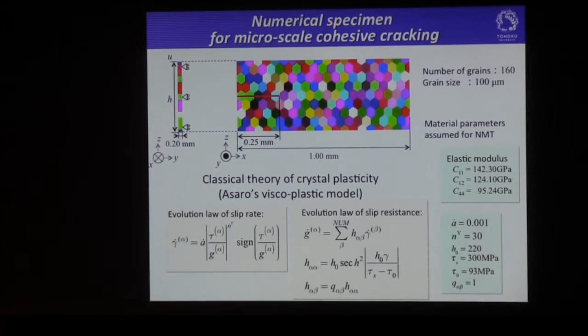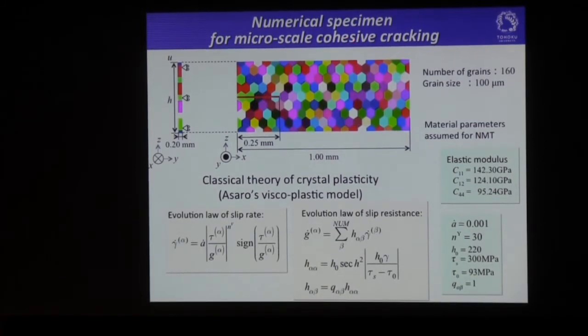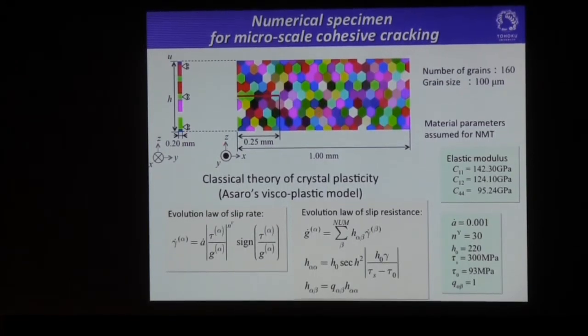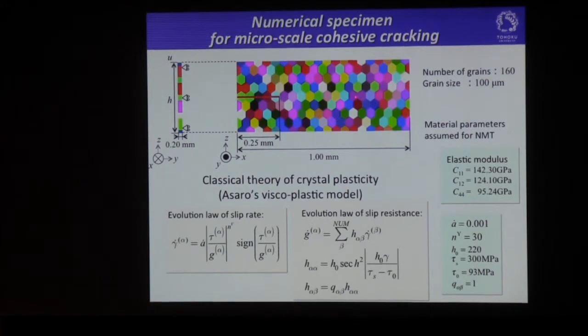Okay, this is the numerical specimen for my microscale cohesive cracking. This is a kind of polycrystalline aggregate. In order to represent the plastic deformation of this material, we employ the classical theory of crystal plasticity as well, with this evolution law of slip rate and also the slip resistance like this. These are the material parameters I assumed for the numerical material testing here.